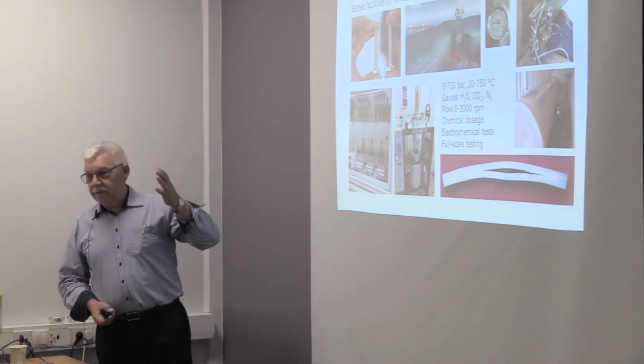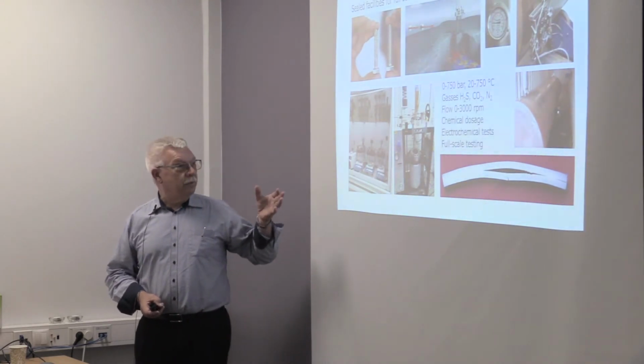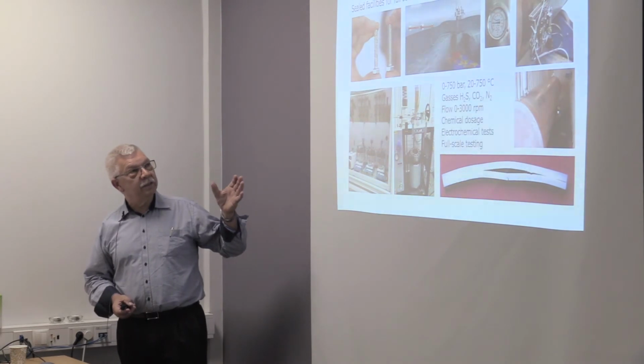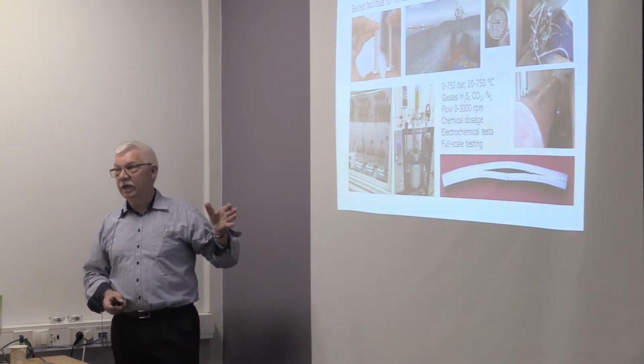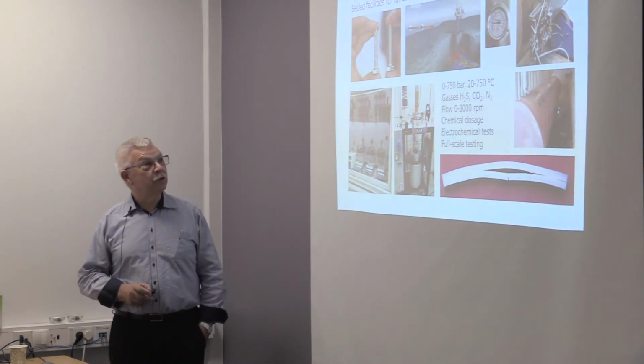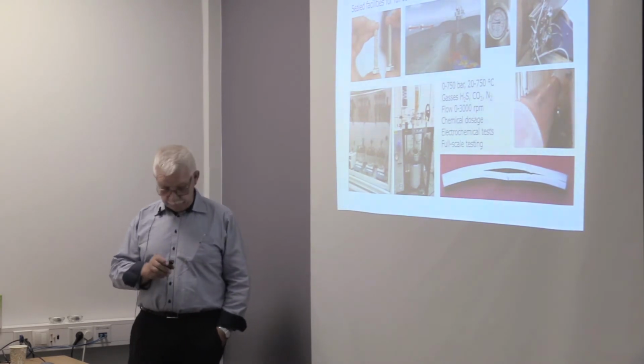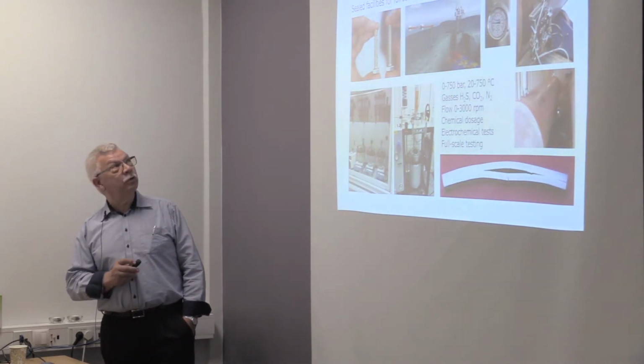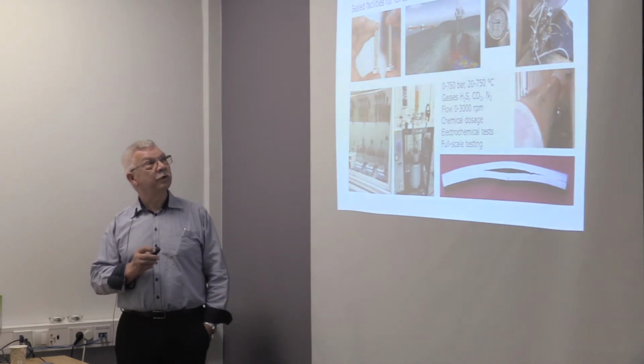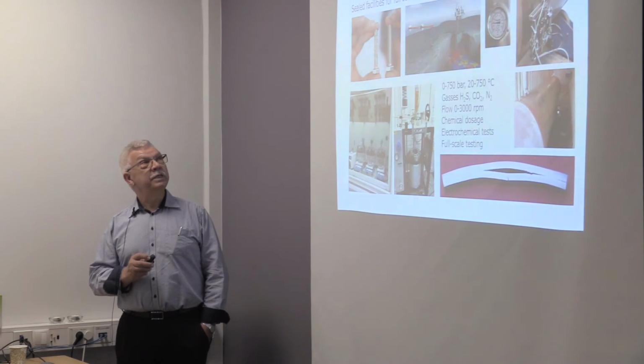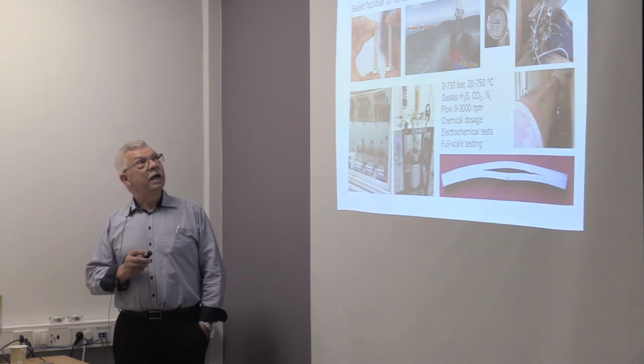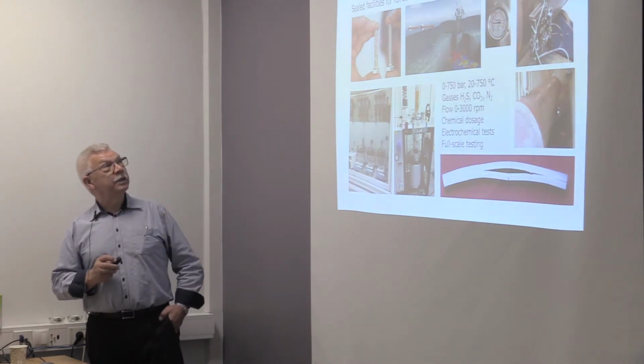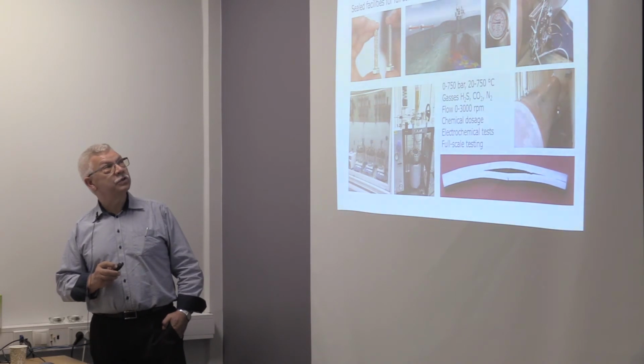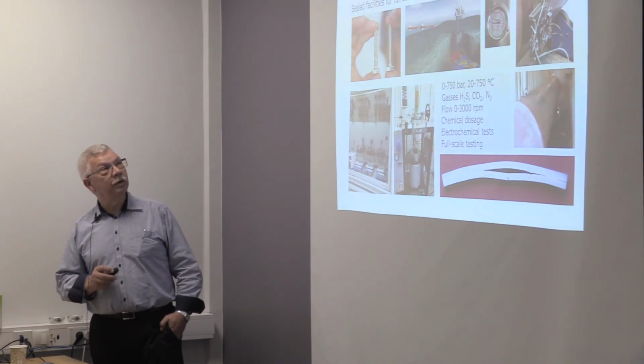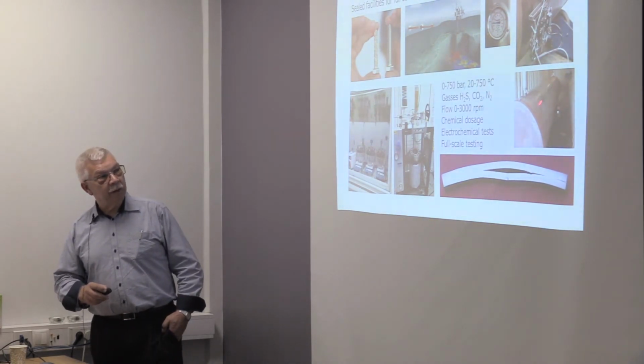We saw before the test on the geothermal plants in Iceland, that has been tested at high temperatures and high pressures to see which materials would be sufficient there. And in fact, that's something that you do in autoclaves, and we have recently acquired a large autoclave laboratory so that we can test specific media at high pressures, high temperatures, and with media meeting the actual conditions. Also full-scale testing of up to a certain size of piping or such.